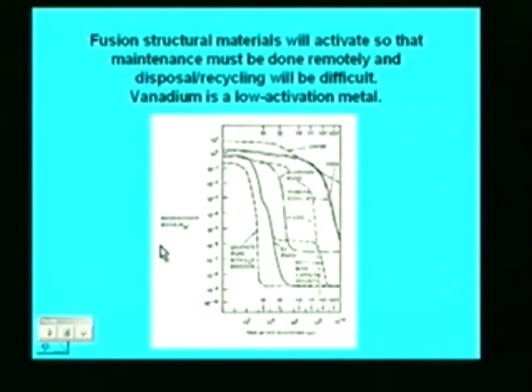Okay, I'm going to talk about vanadium a little bit. And the first question is, why vanadium? Why would anybody want to use it in either a fission or a fusion reactor? And what I've plotted here is induced radioactivity in a fusion reactor as a function of decay time. We have various materials here like graphite and silicon carbide, not a real exciting structural material yet. If we look at stainless steel, we notice that that curve doesn't drop very fast. And we're out here 100 years after shutdown, and we still have something that's quite radioactive.